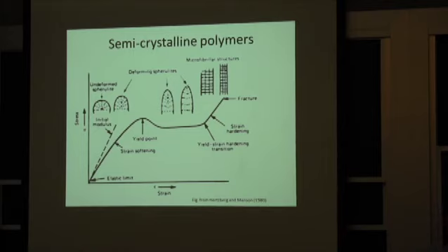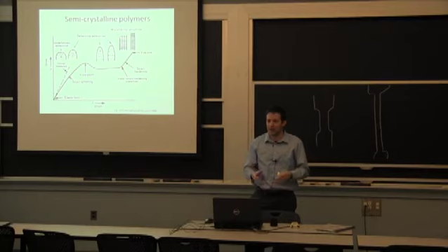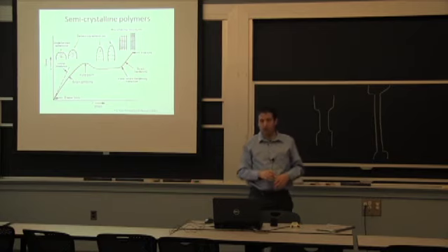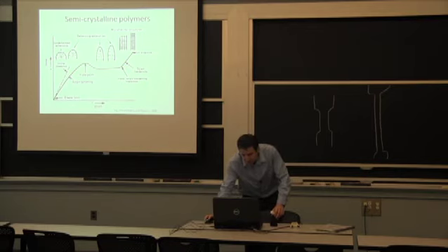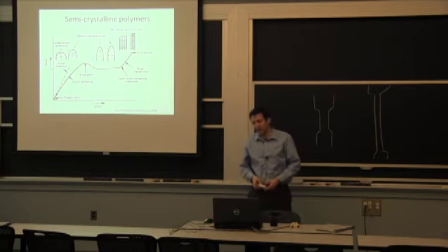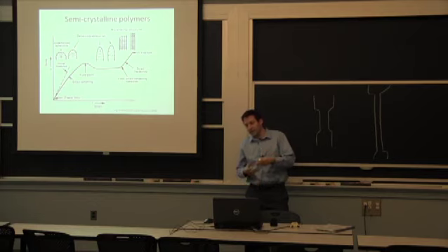It's something that happens also in making that pipe, and that's why you get very different properties than if you start with that, I'll call it a solidification structure, or a nucleated and crystallized, semi-crystallized structure. The semi-crystallized structure is going to deform under a lower load, and at the beginning it has hardening, but it doesn't have that much hardening. That's why you get into forming a neck very quickly. But when you're down the road here with a nylon wire or a nylon rope or anything like that, it's so stretched, and it's fairly resistant to very small imperfections, but it is notch sensitive, and we can go through that as a disadvantage for a design later.